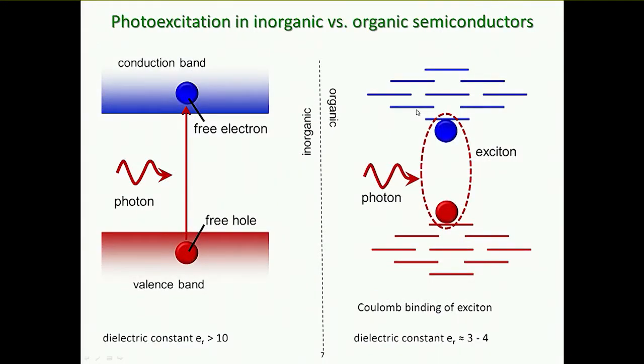Not only that, if we look at the nature of a photoexcitation, in solar energy conversion you want to absorb a photon and generate free charges. This happens relatively spontaneously in an inorganic semiconductor. And in the case of our disordered semiconductor material, which also, because of the low molecular weight of the atoms involved, has a low dielectric constant, we tend to generate a state which is locally bound, where the electron and hole are tied together, and a relatively large amount of energy is needed to liberate the charges and allow them to move freely. That creates a problem for solar energy conversion.